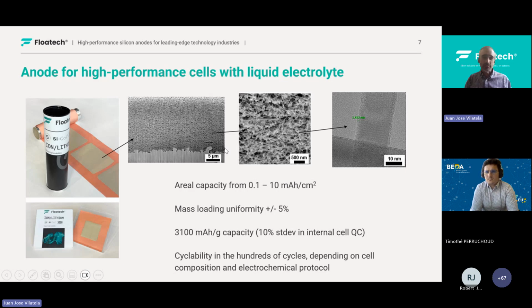If this is of interest to you, if you look inside, this is essentially a porous network, and this is important because that way it contains the expansion of the anode active material within the pores. Capacity of the anode, about 3,100 milliamp hour per gram, and cyclability in the hundreds of cycles. And any cell producer would want to know more details, which I'm happy to share offline.